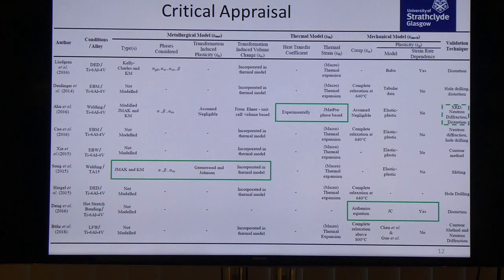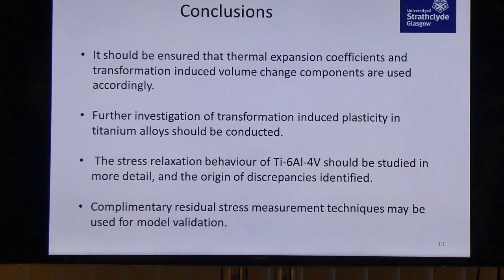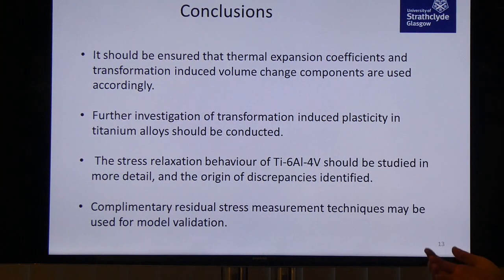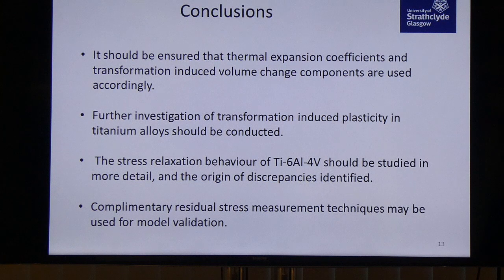The conclusions are: thermal expansion coefficients and transformation-induced volume change components must be used consistently to prevent any duplication. Further investigation of transformation-induced plasticity in titanium alloys should be conducted, as this is particularly lacking compared to the extensive work done for steels. Stress relaxation behaviour should also be studied in further detail, as it is important for ageing and annealing applications but has little quantitative data or predictive application. Finally, complementary residual stress measurement techniques should be used to gain a full understanding of what is occurring in the part.